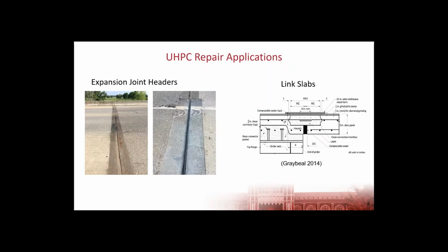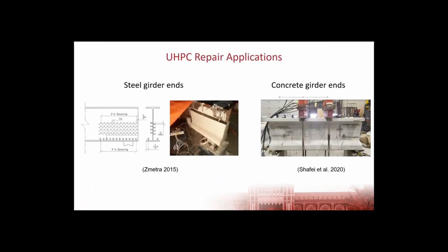In other states, there's been a lot of work done with UHPC link slabs that are used both in new construction and even removing some of those joints in the deck and spreading out the joints to the end of the bridge. Previous research has been done on repairing steel girder ends with UHPC, so kind of as an encapsulation with shear studs on the girder web to strengthen the end of a corrosion damaged steel girder. And then some recent work has looked at using UHPC as kind of a patch repair on the ends of precast pre-stressed concrete girders.